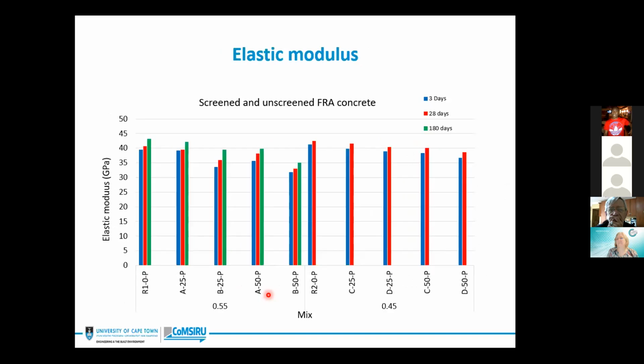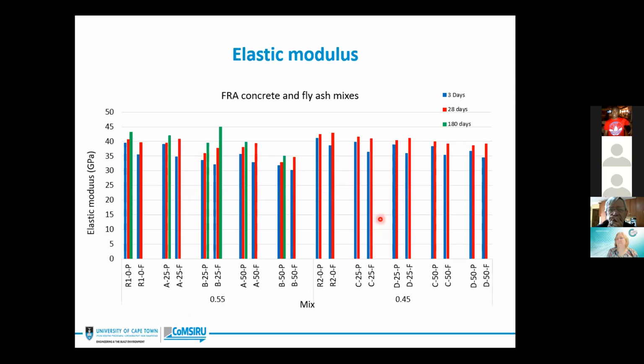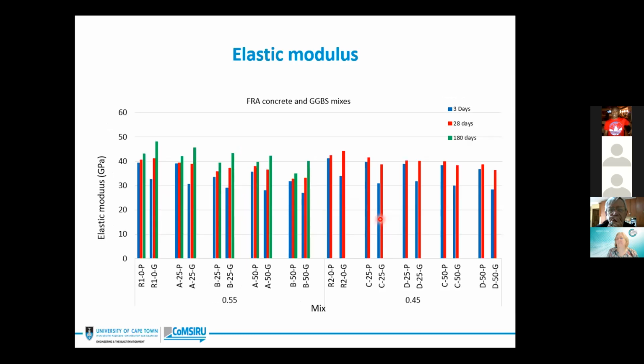Now for elastic modulus, we can see that most of the results we have here are for 28 days mixes. Generally, elastic modulus is largely dependent on aggregate stiffness and cement paste content. Therefore, an increase in FRA content results in a decrease in elastic modulus. Also, screened FRA mixes having less adhered cement paste and more stiffness show a higher elastic modulus than their corresponding unscreened mixes. Here are the screened mixes, here are the unscreened mixes, and you can see that. So a similar trend is observed for fly ash and GGBS mixes.